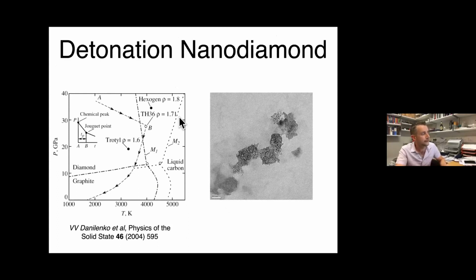For a very short period of time in a detonation, you have this high pressure and temperature that gives you your diamond, for about a microsecond, and you get about 5 nanometers. The problem is for the rest of the shock wave, you get stuff that isn't diamond. And that's really bad, because when you go and look in your TEM, you have loads of little particles stuck together by all sorts of rubbish.